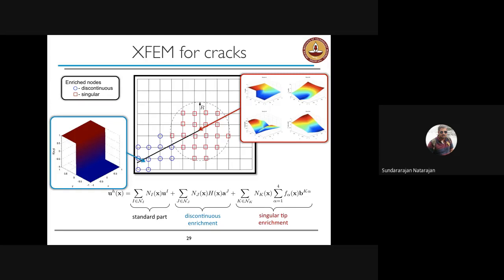And if you're using finite elements, that is represented by the standard part, since the functions Ni of x, those are the basis functions, they are continuous functions, they cannot represent either the crack tip singularity or the jump in the solution, right? To be able to model this, we add two sets of enrichment functions here. One that can capture the jump, so these functions are restricted to regions behind the crack tip, and one set of functions which can represent the singularity, which is ahead of the crack tip. And by doing this, we can now capture the necessary physics of the problem without having to update the mesh.